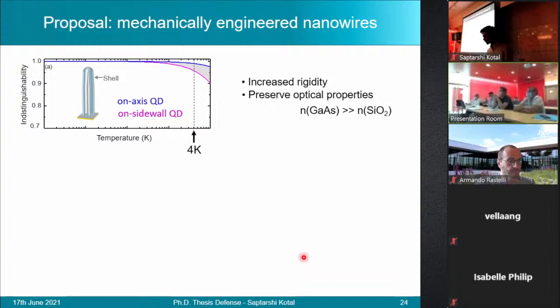First, we can conceive of coating the entire nanowire with a dielectric shell. Here we use a 500 nanometer shell of silica. By adding the shell, we increase the rigidity of the system, thereby reducing the coupling between the quantum dot and the modes of the nanowire. And as we notice from the graph in magenta, which corresponds to an on-sidewall quantum dot, in the worst case scenario, we have an indistinguishability of around 95%.